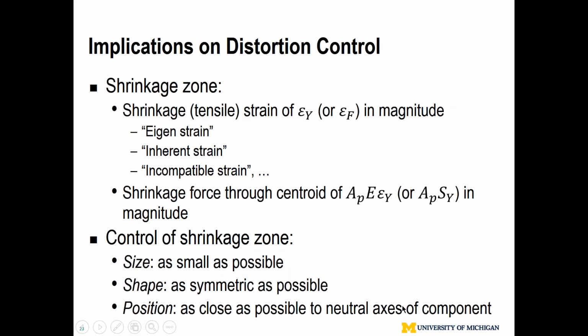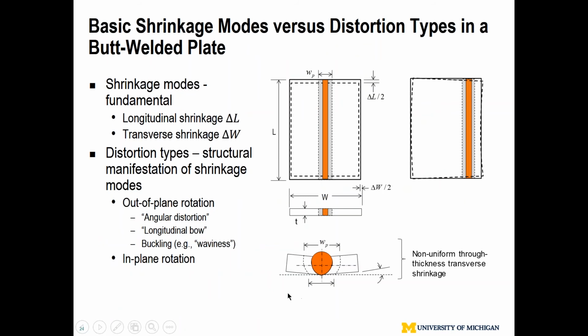So now, up to this point, how are we going to control distortion? Let's control the shrinkage zone. You want to make the shrinkage zone, the plastic zone, as small as possible. You want to make the shape of the plastic zone as symmetric as possible. And then here's the more difficult one. The position of the plastic zone, the neutral axis of the plastic zone, the shrinkage zone, has got to be as close as possible to the neutral axis of the component at that moment in time during assembly. So very easy: size, shape, position. Position is a design problem. The design engineer needs to be aware of the shrinkage phenomena. So the designer should try to put the weld at the neutral axis, at a symmetric position as much as possible, to make the weld seam as symmetric as possible.